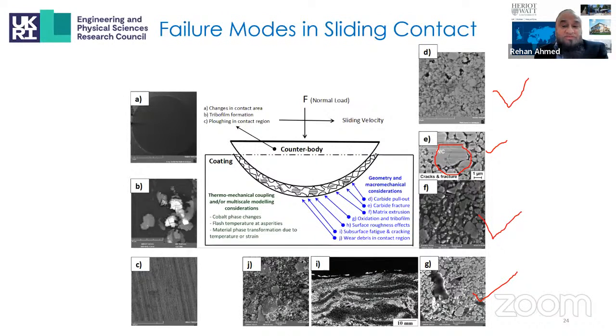And in most cases for these coatings, WO3 is the most dominant tribofilm, which reduces both the wear rate and the friction. Now, repeated sliding can also lead to near surface and subsurface cracks, leading to coating delamination, as shown over here. And then the changes in the wear mechanism from two-body abrasion to three-body abrasion, which can be caused by the entrapment of the wear debris within the contact region.